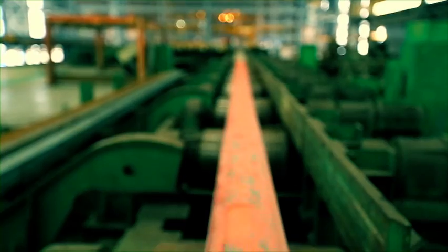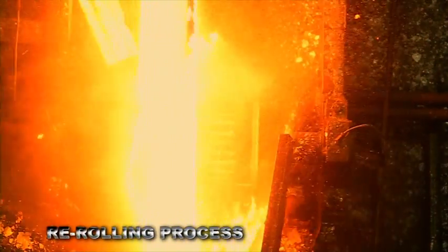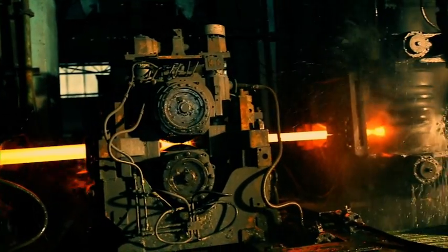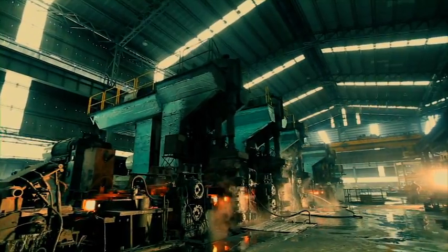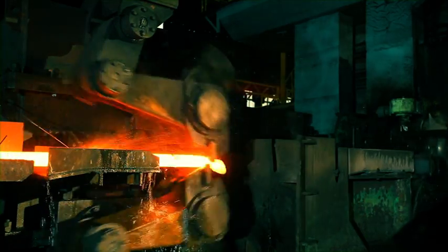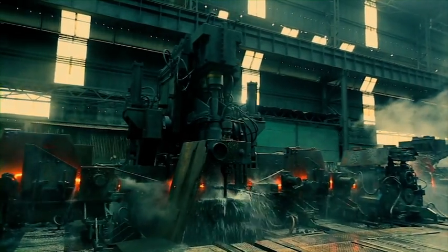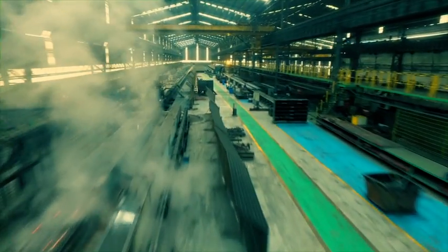The produced billet is reheated in a furnace and automatically enters the synchronized rolling mill process. AKS rolling mill consists of a state-of-the-art 18-stand rolling line. The special feature of this rolling technology is the combination of horizontal and vertical rolling, which allows rolling of the billet without altering its mechanical properties. The rolled bar from the hot rolling process passes quickly through the thermomechanical cooling system, resulting in different temperatures in the core and outer layer of the steel bar, which is critical for achieving high strength yet high bending properties.